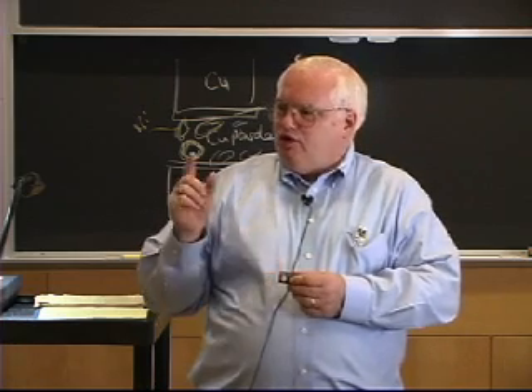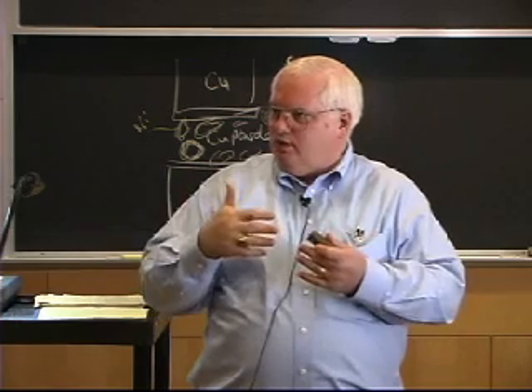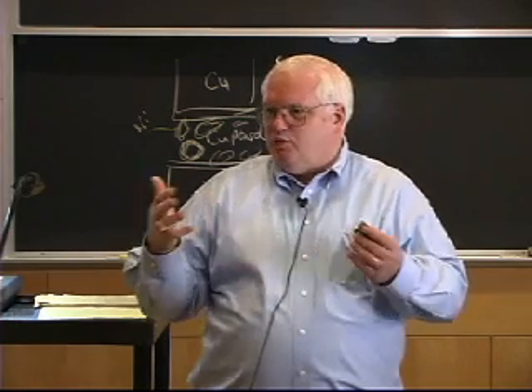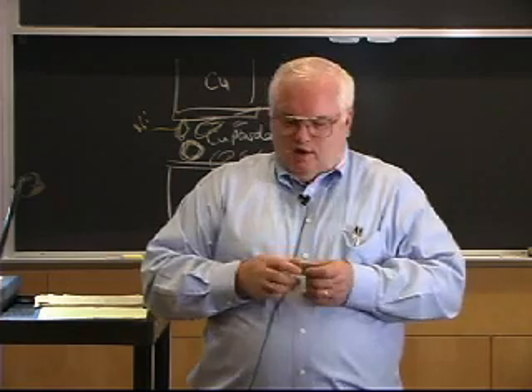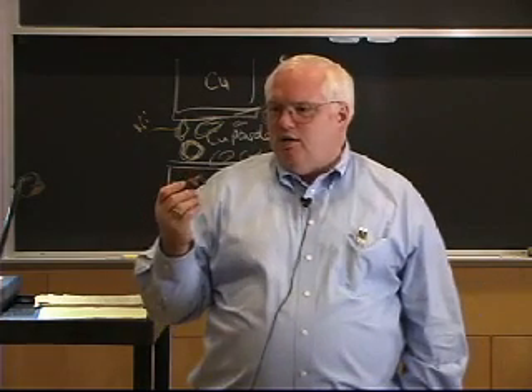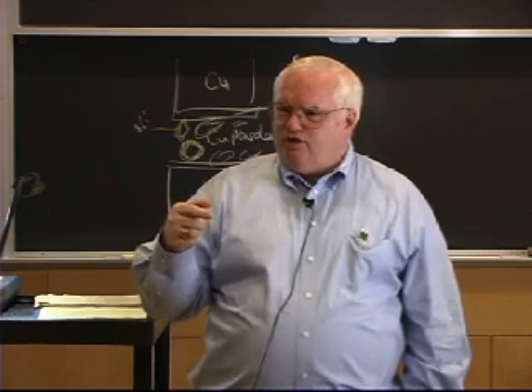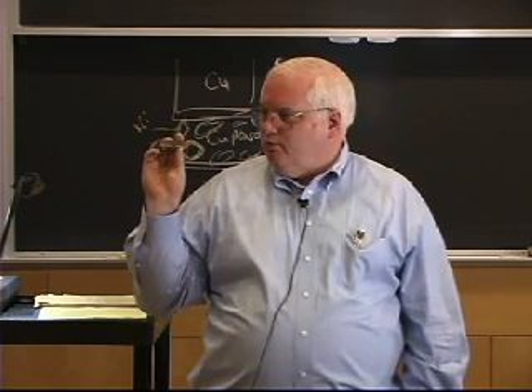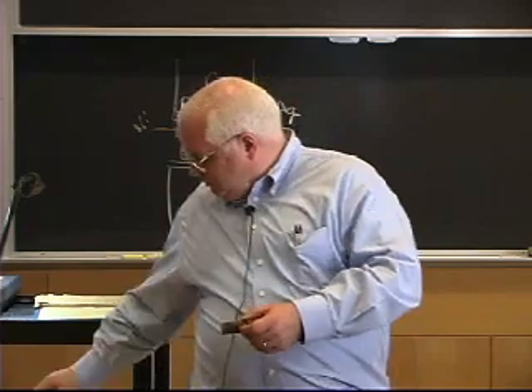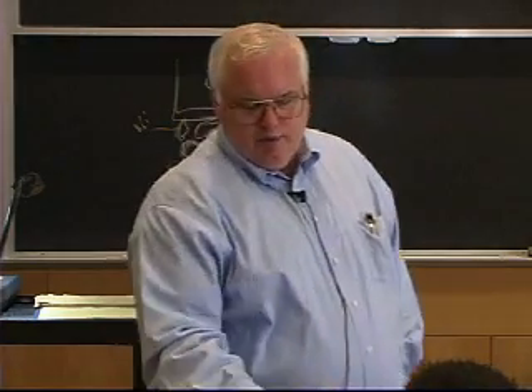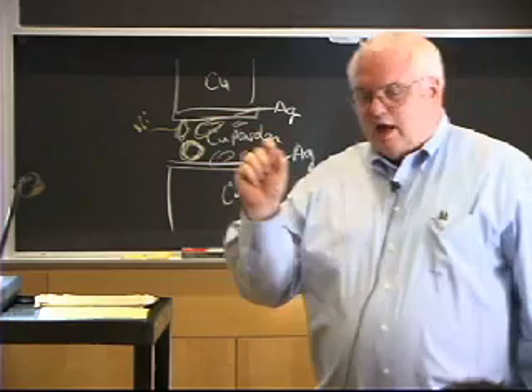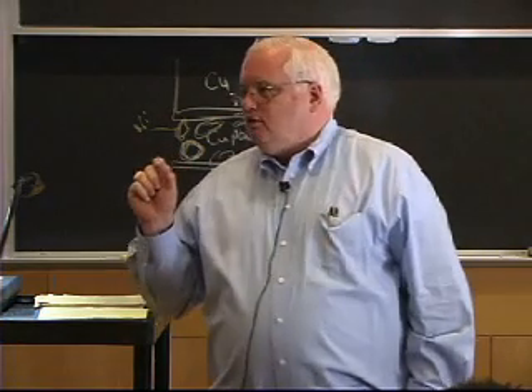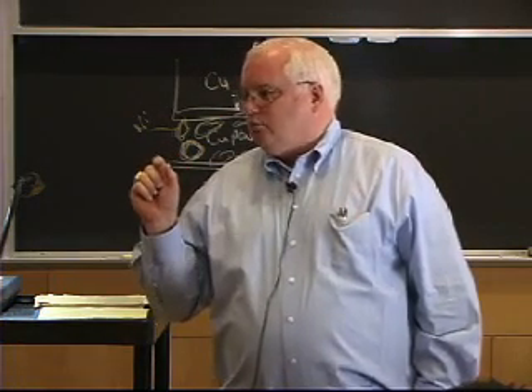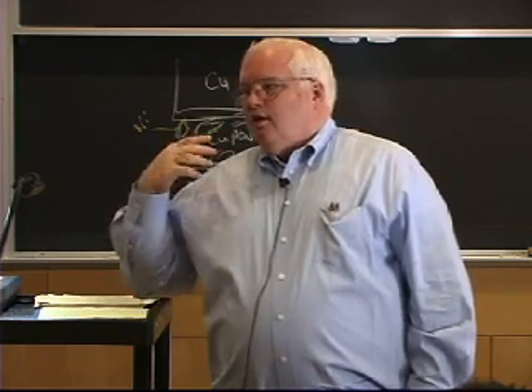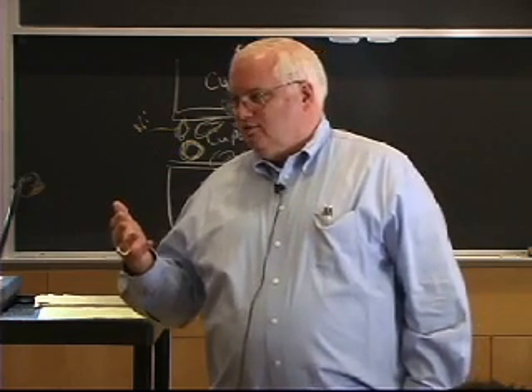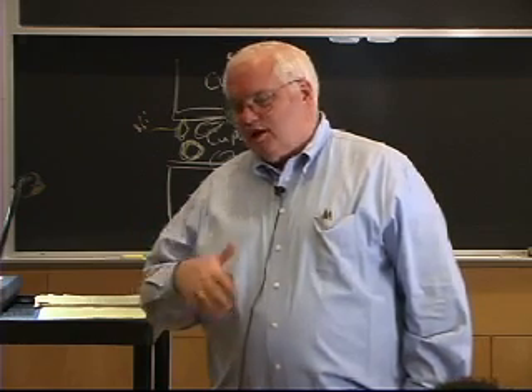However, if I hold it at temperature, the nickel will diffuse into the copper, but it takes a little bit longer time. It's not liquid erosion, it's solid state diffusion. So over a couple of minutes, the thin nickel layer dissolves into the copper. Now the silver reacts with the copper and makes a TLP bond. So this whole thing, and the student machined it so you can actually see that it's a homogeneous solid joint. That's probably the thickest TLP joint I've ever seen, by far. But you had to do something to stop the diffusion initially, or slow it down initially. So that's the trick on that one.